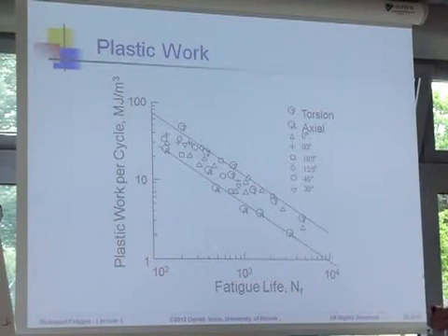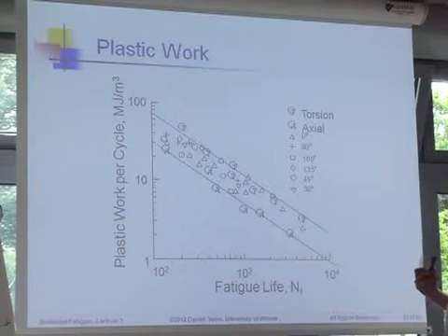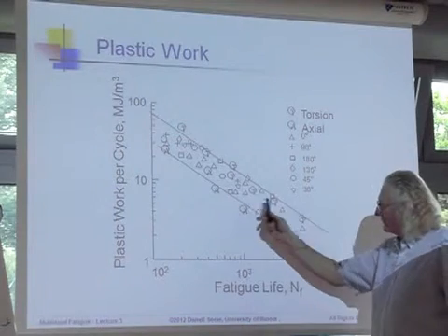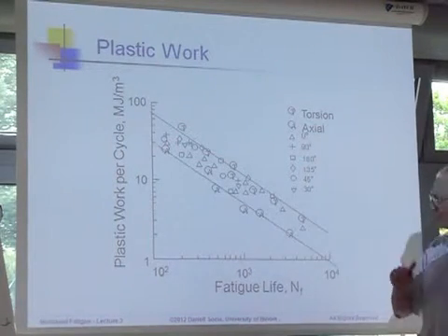And if you look at all of the data, what I have found is that all the data, of course, scatters between the axial results and the pure torsion results. And of course, it scatters by about this factor of 2. Right? And then people do things which are really strange. They say, well, okay, I make this observation, and so torsional work is only half as damaging as tension work. And of course, you can collapse all that data. Right? Absolutely wrong. Absolutely wrong.